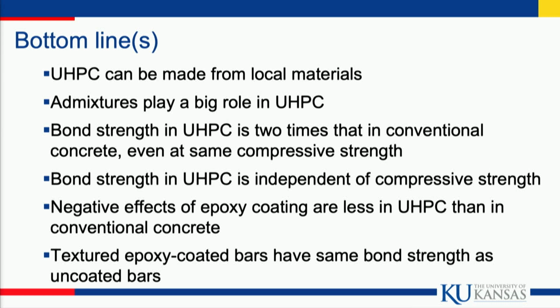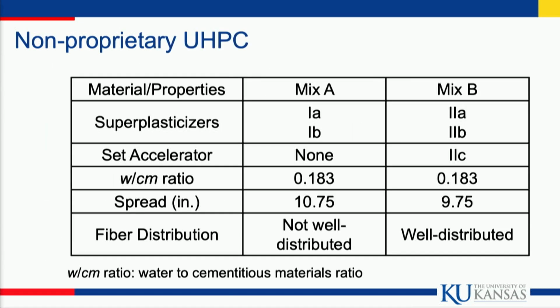The negative effects of epoxy coating are much less in UHPC than in conventional concrete, and the textured epoxy-coated bars do give you the same bond strength as you get with uncoated bars. This is an example of the work we've done. This is all with ODOT approved materials.